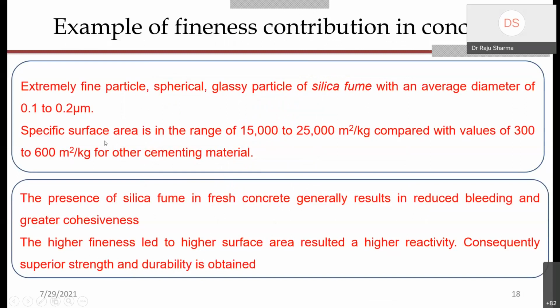If you see silica fume, it is an extremely fine particle. It is spherical and glassy, with an average diameter of 0.1 to 0.2 micrometer, right? And the specific surface area is in the range of 15,000 to 25,000 square meters per kg, compared with the value of 300 to 600 square meters per kg for other cementing materials. So these are the physical properties of silica fume. Now, how can you collect this information to make the reasoning for your research?